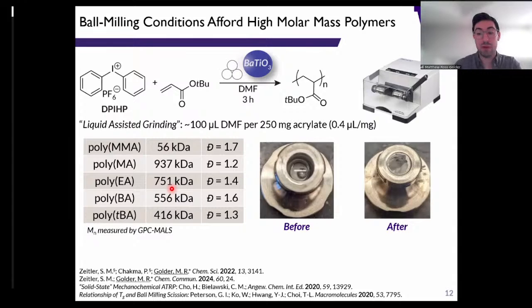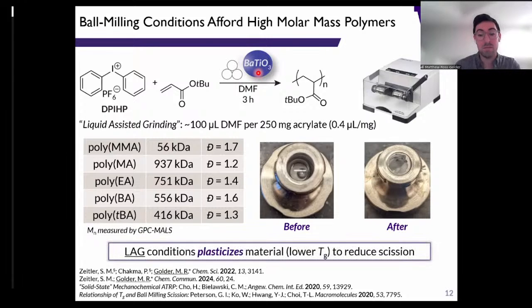Looking at these reactions pictorially, right, we start with something that sort of looks like sand in a puddle with a single ball bearing here. And after we shake around for a bit, we end up with this essentially polymer composite. We can dissolve the polymer up and precipitate out the particles and reuse and recycle them in subsequent reactions.